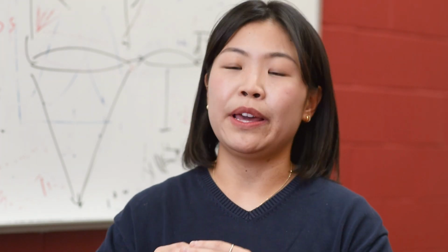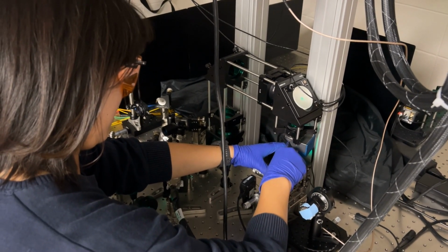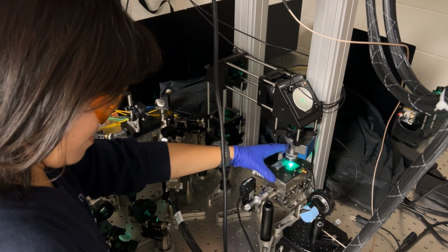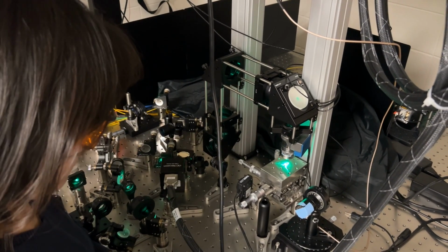And also silicon has a much higher refractive index compared to the diamond, so that light can efficiently get out rather than being trapped inside the diamond. The reason we call this an antenna is that we can get more light out from the NV center in the diamond and then redirect the light into free space. But silicon is the most widespread material that the industry is currently using. All the electronics now have silicon inside. So that means we can scale up this invention and it can be used directly in the industry.